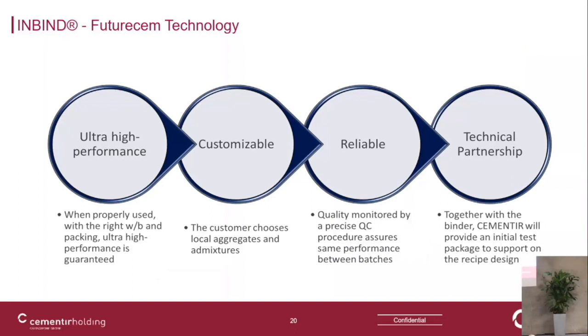If we must condense the main benefits of InBind in one slide, this is it. When you use InBind with the right aggregate and a water binder ratio between 0.21 and 0.27, ultra high performance is guaranteed. It's a flexible solution with total customization, because you can use your local sand, your local admixture, and the fiber from your local source and your local partners. The performance of InBind is very reliable because it will not change batch to batch, thanks to your continued quality control with the QC.